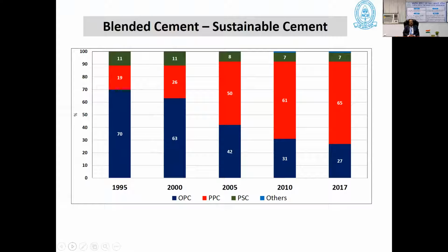Now you see the blended cement distribution in India. In 1995, you will see the figures, that is 70% OPC, 19% PPC, and 11% other Portland slag cement. With the advancement of years, by 2017, you see that 70% OPC has become 27% OPC, 19% PPC has become 65% PPC, and 11% PSC has become 7% PSC. And here in this figure you see that 65 plus 7, 72%, is the total blended cement produced out of 100 in India.